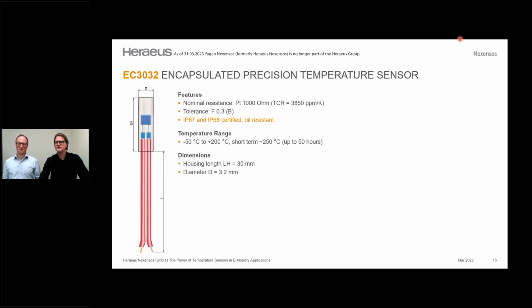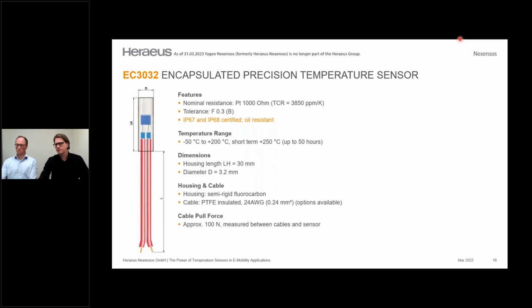The dimensions, this is why it's called EC3032, is the housing length of 30 millimeters and the diameter of 3.2 millimeters. And the cables are in this situation a semi-rigid fluorocarbon cable, and the isolation is a PTFE insulation with 24 AWG. But this is all discussable. That means if you need very special things, we can talk about it. The cable pull force, this is also a very nice indicator of how good the connection is between cable and sensor, is here at 100 newtons, which allows us to work with that system in a very good way. The electric strength is tested with 6,000 volts alternating current, and it withstands that for over 60 seconds.